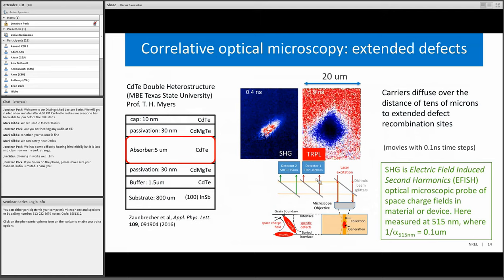This is because carriers drift and diffuse to the extended defect at the center of this image, and this single extended defect impacts recombination over the spatial scale of more than 20 microns. From the analysis that I will show in the next slide, we can quantify the various parameters that describe this recombination.